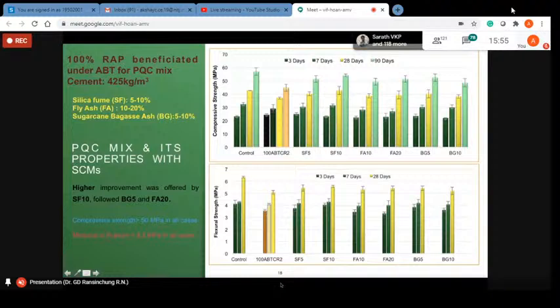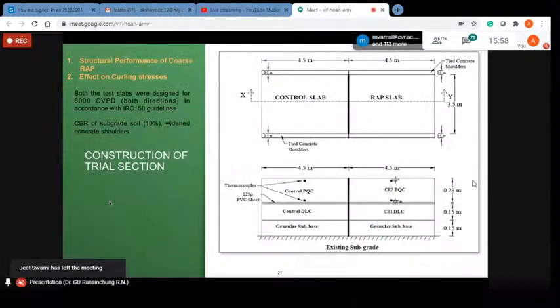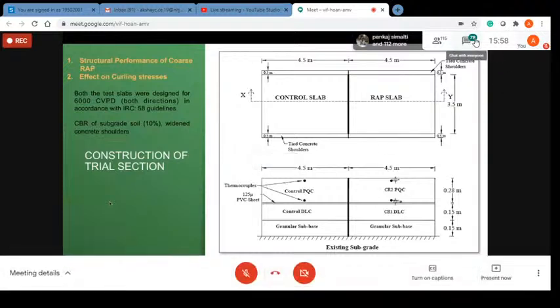Now, in the construction of this trial section, the GSB layer that we have considered is 150 mm, dry lean concrete of 150 mm, and PQC slab of 280 mm. This particular pavement was designed for the traffic of 6,000 commercial vehicles per day, both directions, in accordance with IRC 58 guidelines. And we have considered that the CBR of the subgrade was about 10%. Because this particular trial section was carried out on the existing pavement section, and we have assumed that there has been a sufficient consolidation effect. Therefore, the subgrade CBR of 10% was considered.